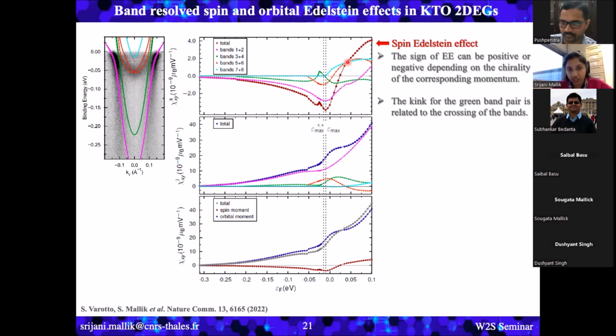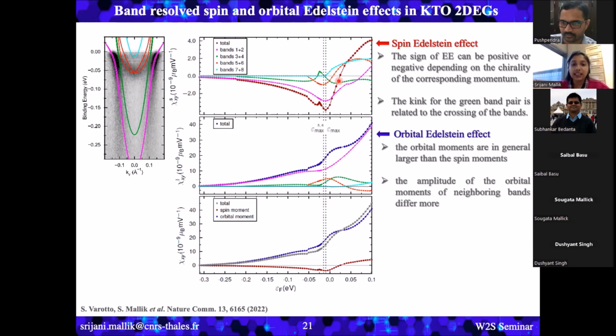So there is a strong compensation effect in the total Edelstein effect happening here, which we can see because of these opposite signs. And when we calculated the orbital Edelstein effect, one very good thing we observed is that the orbital Edelstein effect is 10 times larger than the spin Edelstein effect. And so far, experimentally, we could measure only the spin Edelstein effect. We have never measured the orbital Edelstein effect. So this means that if somehow we can include the orbital Edelstein effect also in the measurements, this will give us much higher spin to charge conversion.